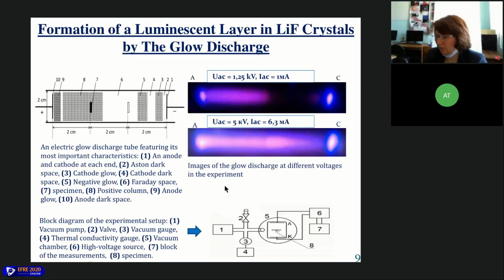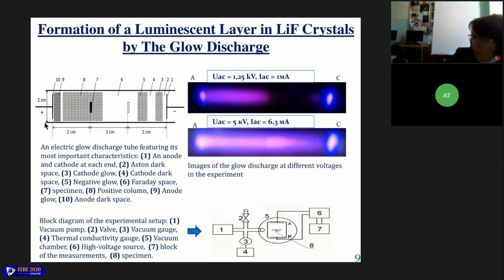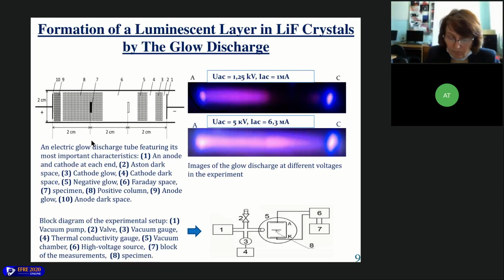The experimental setup is composed of a vacuum chamber, inside which you can see a glass tube, scheme is here, with a diameter of 2 centimeters. In the chamber, glow discharge was formed in air at a pressure of 50 Pascal and at 1.25 kilovolts. A glow discharge at such pressure is characterized by the presence of major extensive regions, namely the positive column, you can see here, and the Faraday dark space here.